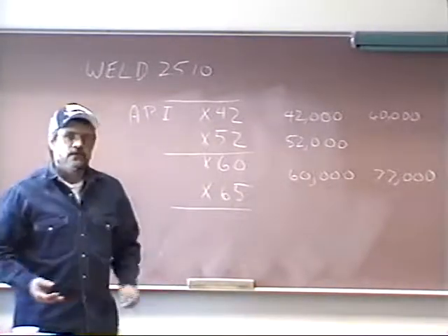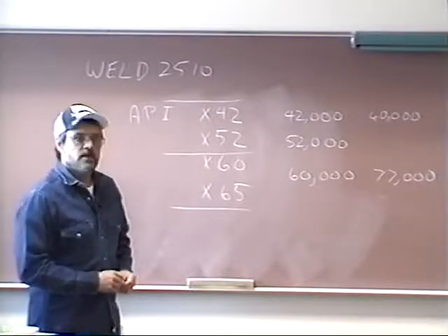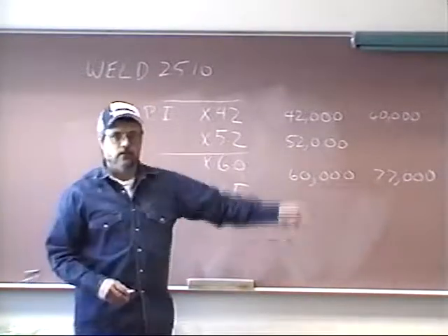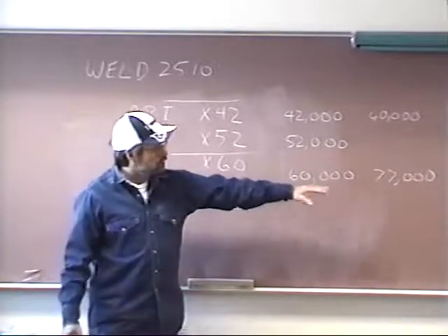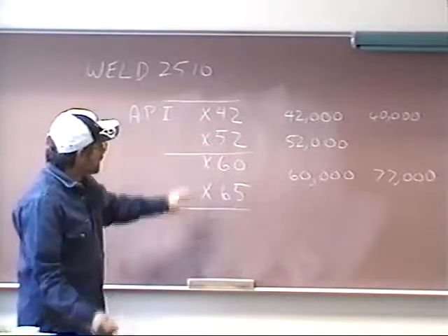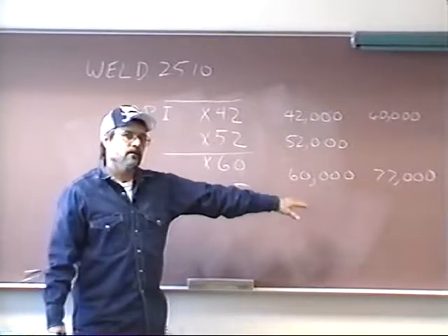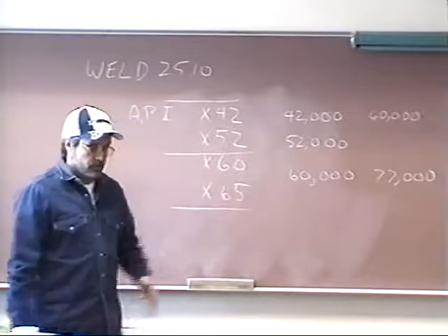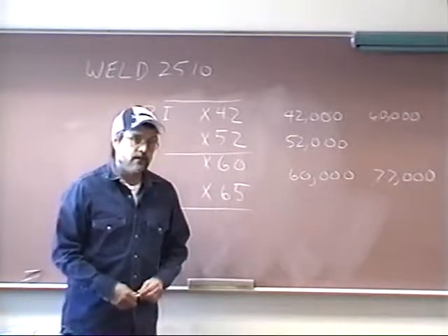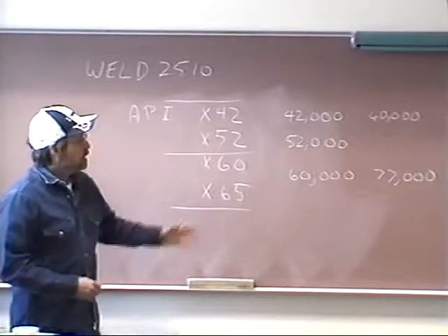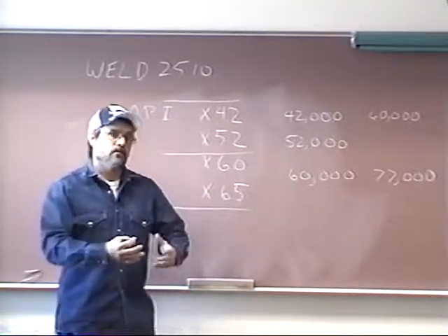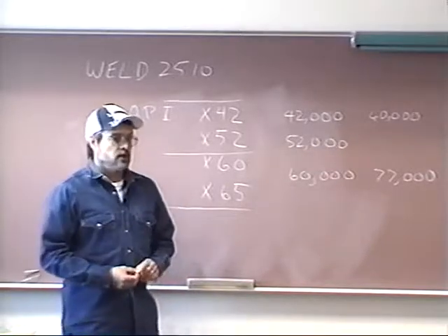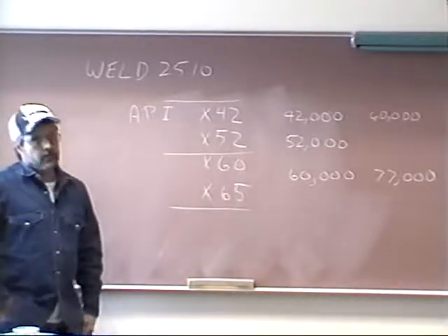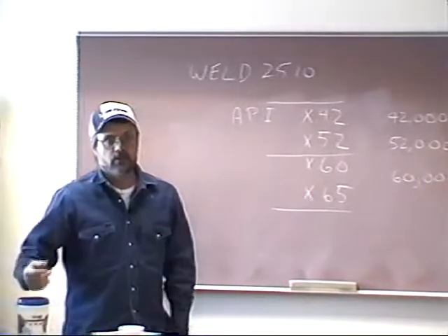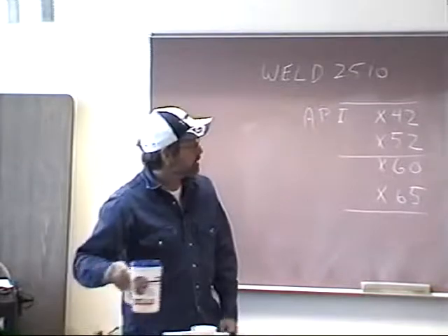Here, if you're welding X42 or X52, we may just take a rosebud or a cutting torch and drive the moisture out of the weld, and then we'll go ahead and put our weld in and be done with it. Here, because we have much higher tensile strengths, we're going to preheat that up to 200 degrees. We're going to take special care to make sure it's preheated to 200 degrees. Then we're going to produce our weld, and then we may want to wrap the weld when we're done. Wrap it with some asbestos blanket or something in order to let that heat dissipate more slowly and relieve some of that stressing. So pay attention to the amount of carbon, the type of material that you're welding. Again, it goes back to you as the welder. Don't trust what anybody else says. If you have an opportunity, read the welding procedure and know.